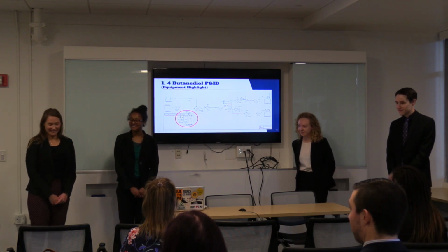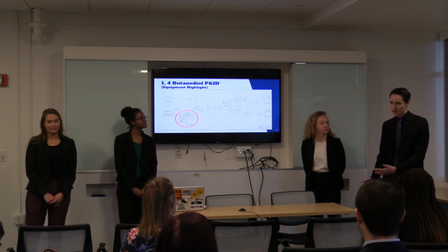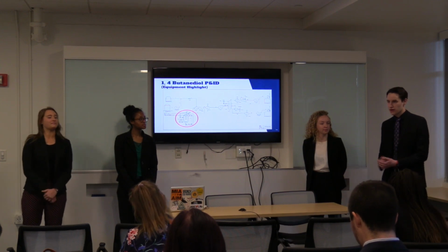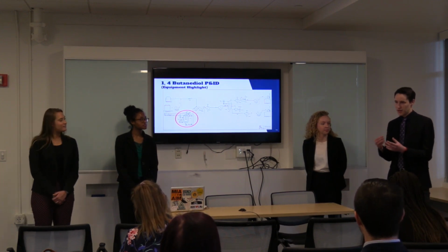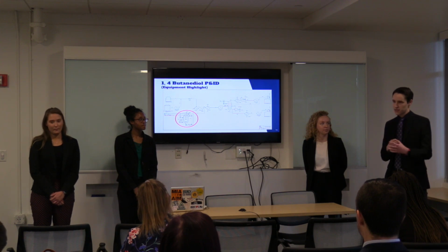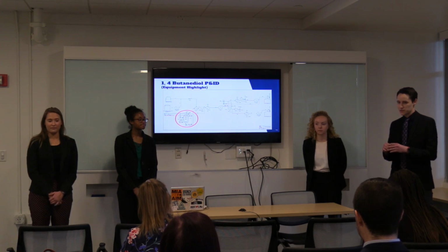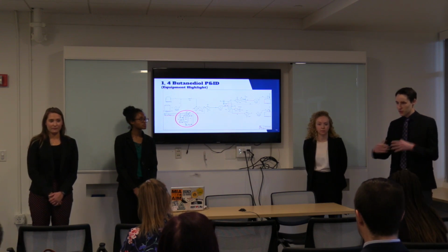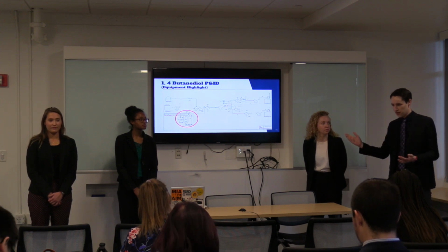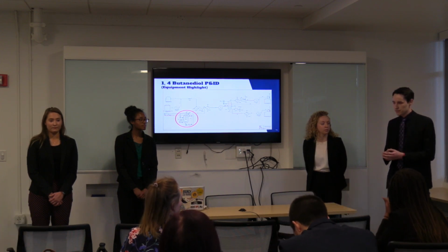I have a couple. What's the mode of degradation for PBS? So it depends on the environment that it's in. For example, if it's kept in water, it slowly decomposes back into monomers, the succinic acid and the butanediol. Within a compost environment, it's broken down by bacteria, and having that rice husk flour biomatter inside helps create pockets where it'll break down more easily. So it slowly degrades into smaller and smaller pieces, on a large time scale of a year or two, depending on the product that's being used.